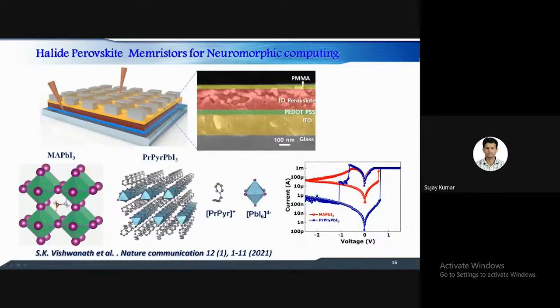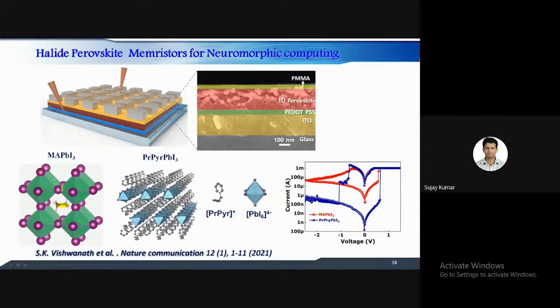What we did is we initially started these memristors with methyl ammonium lead iodide, which is basically a 3-dimensional perovskite. The methyl ammonium stands at the center of the octahedral structure of lead iodides. This circle is iodine, and inside the green portion they have lead, in an octahedral structure. Initially we used MAPbI3, and to protect it we used PMMA as a polymer, which avoids the interaction of the metal with the perovskite. We also used PEDOT:PSS to protect the other electrode from the perovskite.